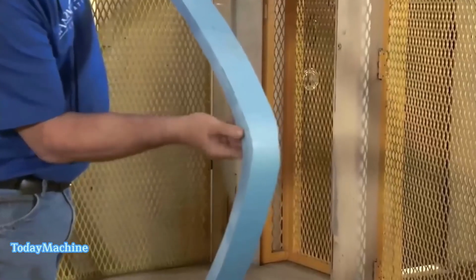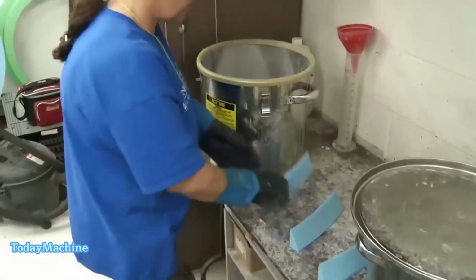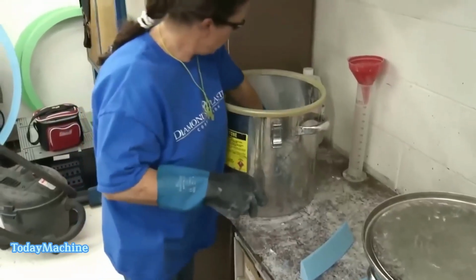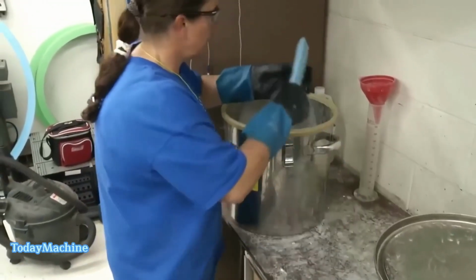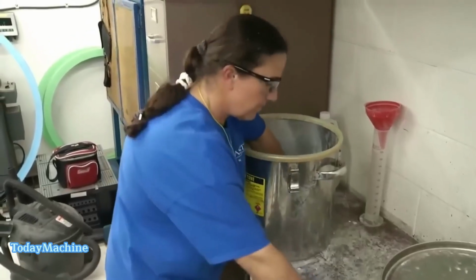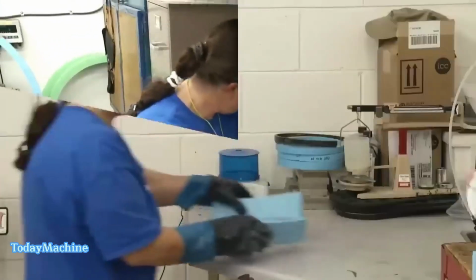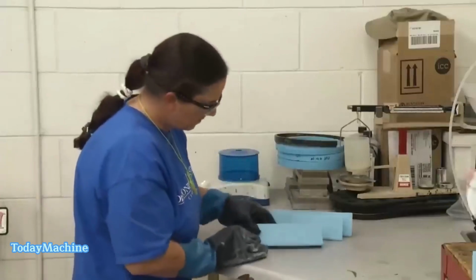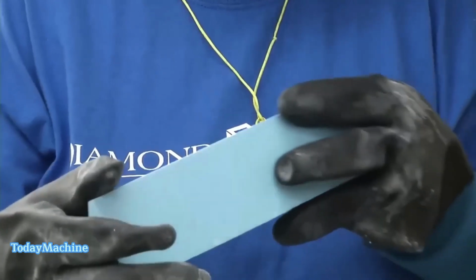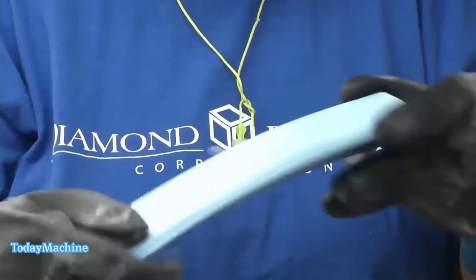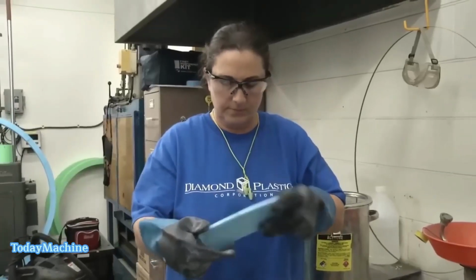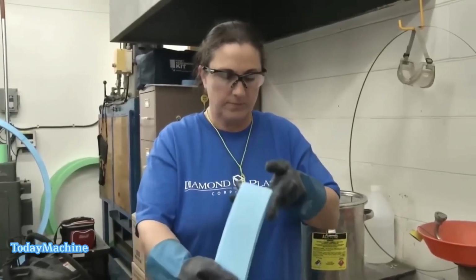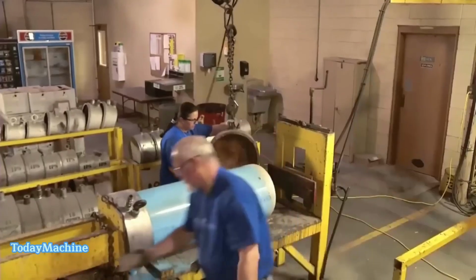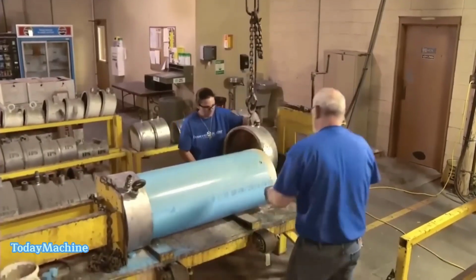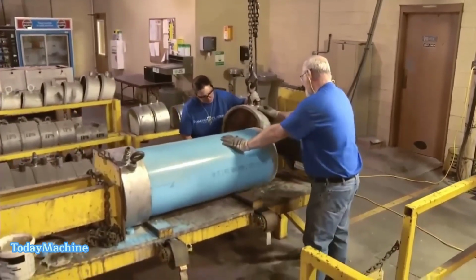Stiffness testing is another crucial evaluation conducted on the PVC pipes. This test determines the vertical load pressure that the pipe can withstand to meet industry standards. A sample of the pipe is loaded into a test fixture, and a hydraulic press applies downward pressure at a prescribed rate. The load applied to the sample and the amount of deflection are measured, allowing for the determination of the pipe stiffness, particularly significant for sewer pipes.